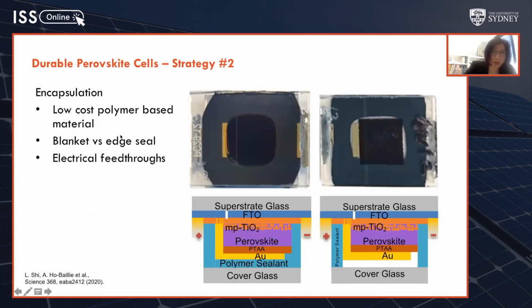We also look at the effectiveness of two techniques, whether you use the polymer to seal the edge of the glass only, which is in this case with a void in between, or we have the polymer covering the entire cell. These are common techniques used for double glazing, for example, or laminate glass, where you have a full area laminate laminating the glass. So in case it breaks, it will hold the glass pieces together. Also, we've got to look at how the electric wires come out of the cell and make sure when they come out, they're not going to let moisture in.